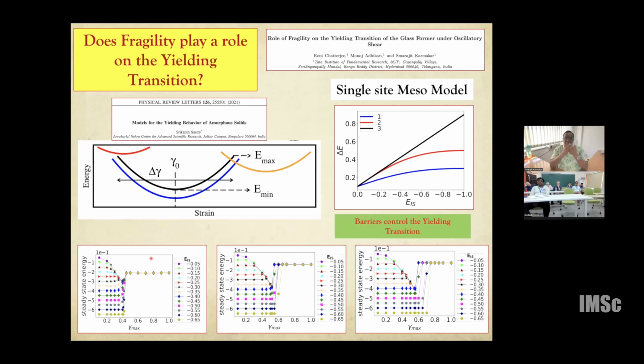But what was missing in this was the difference that one might get if you take a fragile versus a strong glass forming liquid. And what we feel is that the answer lies in how the energy barrier changes in these two types of liquids, and then when you generate glasses from them. For example, for strong liquids it has been shown by explicit calculations that the typical energy barrier does not change with cooling history. Even if it changes when you are in the poorly annealed regime, when you go to the well annealed glass regime, it's more or less saturated. So this is represented by this blue curve. And if you have very fragile glasses, then the energy barrier grows strongly with your annealing protocol or your temperature.